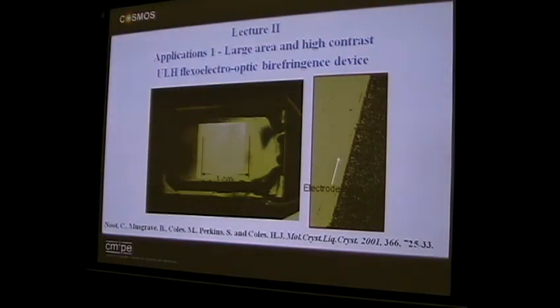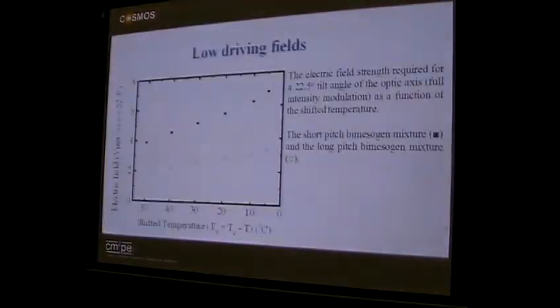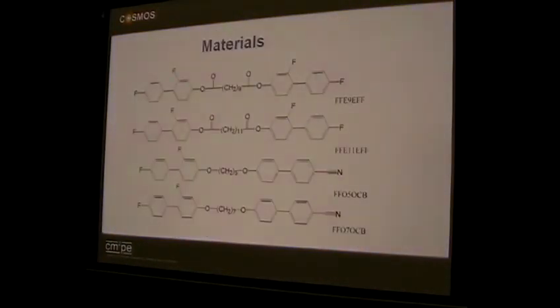But we don't just put one fluorine on. We put two or three or four. Below 100, you are thinking of something with a single component. Any one of these materials would be isotropic to nematic at about 100 degrees, thereabouts. Mix them together, then they'll go from 100 down to about minus 20, the whole nematic phase. It's why you play with the fluorines.